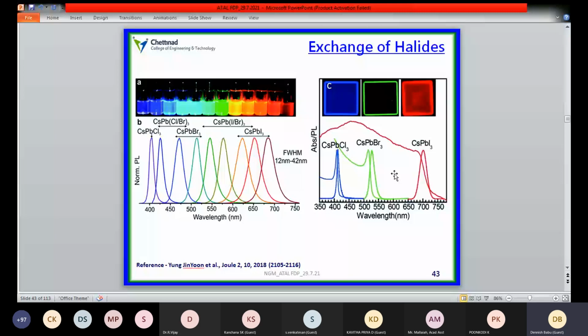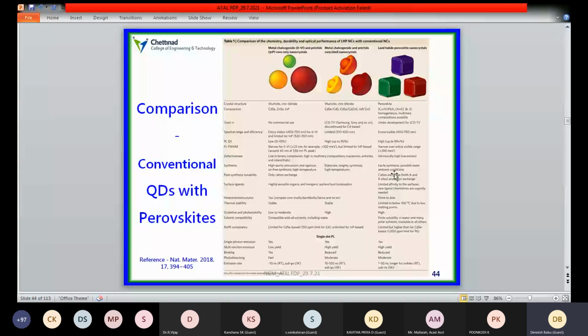In general, we can classify the traditional lead halide perovskite nanocrystals and conventional nanocrystal systems by their crystal structure, composition, spectral range and efficiency, photoluminescence quantum yield, full width at half maximum, surface ligand, thermal stability, multi-excited emission, photobleaching, and emission rate. All these parameters are identified as important for the application of these materials, like core-shell nanocrystals and ordinary metal chalcogenide and pnictide nanocrystals, for device applications. Compared to traditional conventional nanocrystals, the perovskite materials produce high and moderate levels of the properties needed for the fabrication of devices, especially electronic devices.